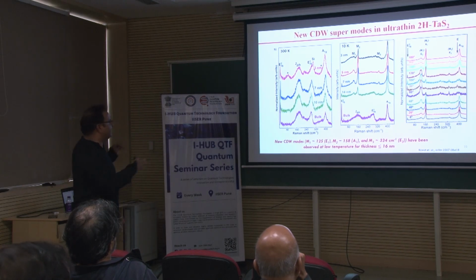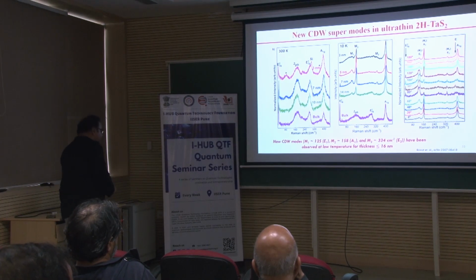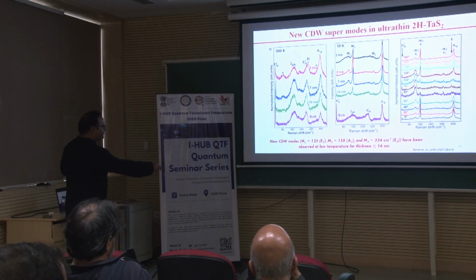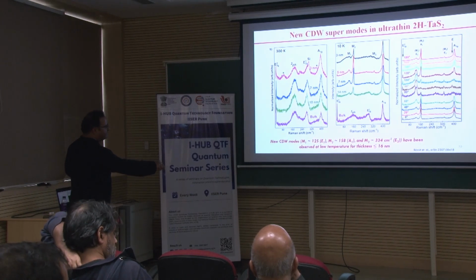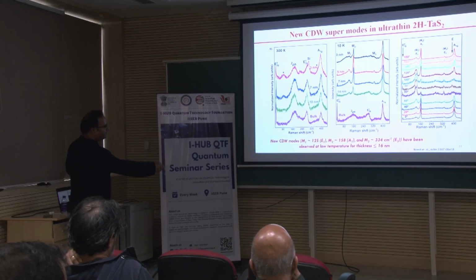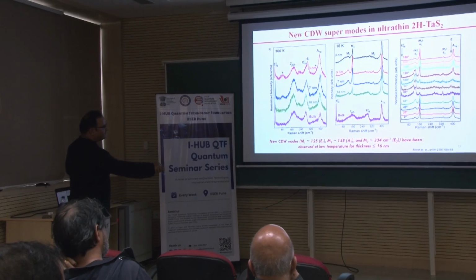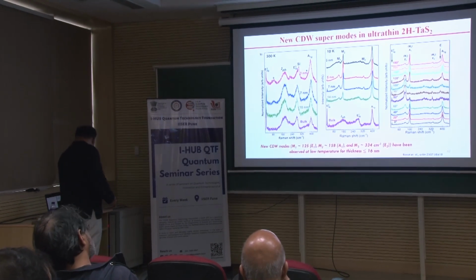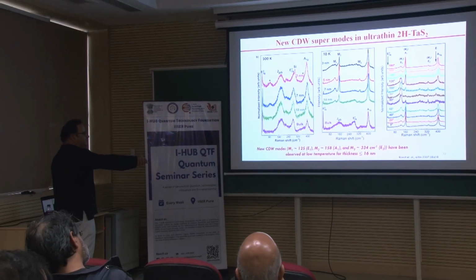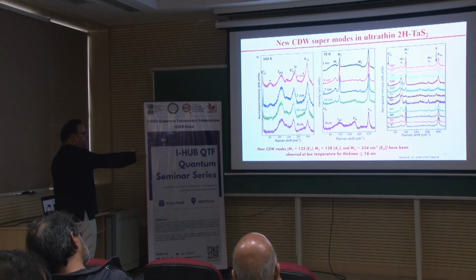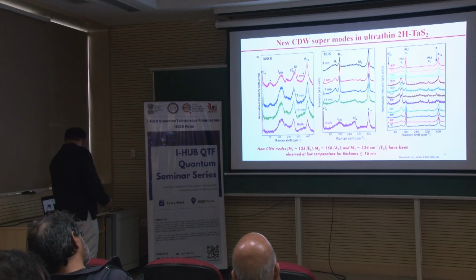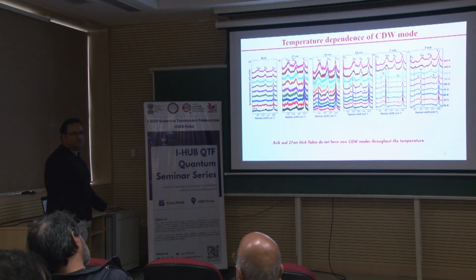We found out that these new modes have a different symmetry. So we have a mode at 125 centimeter inverse, another at 158 centimeter inverse, and the third at 234 centimeter inverse. We identified from the polarization that this is an E mode, this is an A mode, and this is an E mode. Another important aspect is that these modes are available only when you go below 16 nanometer.